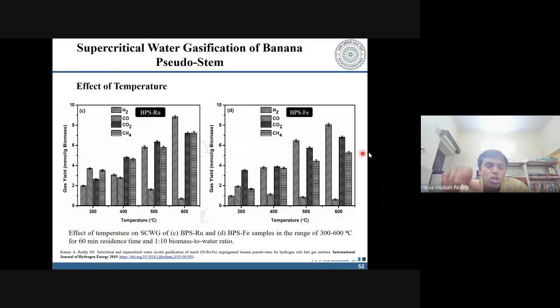If you look at this in situ process, here we don't have any problem of carbon deposition or deactivation of the catalyst. The reason is that we are impregnating the metals right at the front end itself. Now we are treating the metal embedded biomass matrix during the hydrothermal treatments. This metal embedded biomass matrix undergoes the reduction process to form the nanometals during the degradation itself. When it forms the nanoparticles, it has a high surface area. Thereby, it enables the interaction of the intermediates with the metals and promotes the degradation.